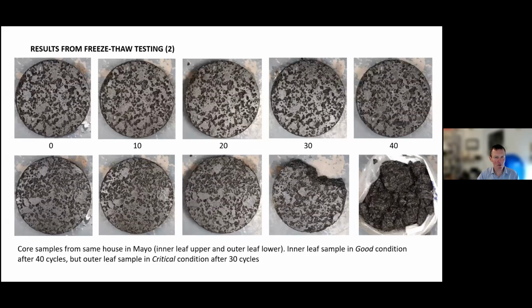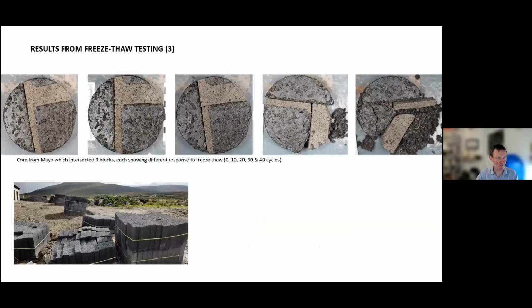So it's something that's very valuable in telling us about the durability. Here's some Mayo stuff. So again, we have one core that remains in good condition for the 40 cycles, and the lower one ends up in critical condition after 30 cycles. It also shows us some really interesting anomalies. So here's a core that intersected three concrete blocks, and you can see a mortar joint in the middle, and each one has a different response.